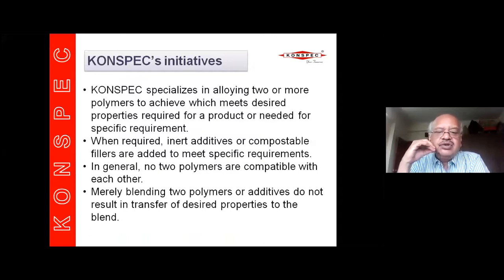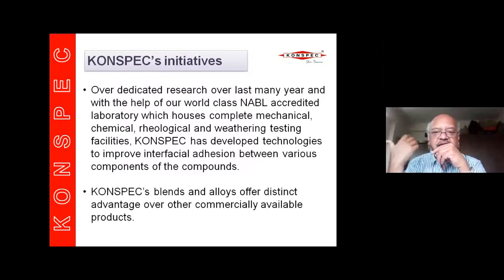Whenever required, we use inert additives like clays or calcium carbonate to increase certain specific properties, say like wear resistance or stiffness. And we also use natural fibers like cellulose or other carbohydrates like starch, or TP starch particularly, to make compounds with conventional bioplastics. I would like to say here that merely blending two polymers or adding an additive to a polymer does not result in transfer of desired properties of individual components to the blend. We need to develop an interfacial adhesion between different components of the alloy or compound.